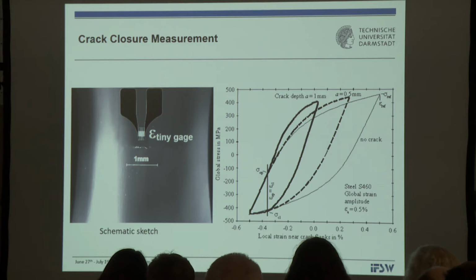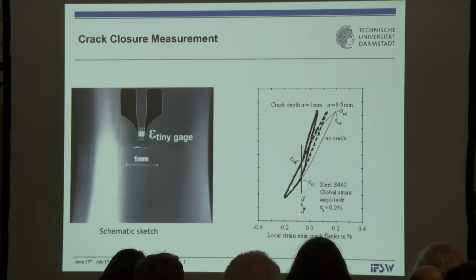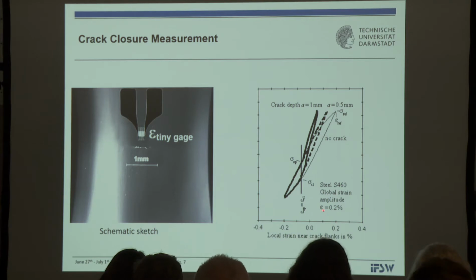This is a figure for applied strain amplitudes of 0.5%, and this is a figure for a smaller hysteresis loop, where the applied strain amplitude is only 0.2%, but the results are practically identical. The loops are a bit narrower, but you identify here the crack opening stress and the crack closure stress, and you can identify a more or less vertical line in this graph to distinguish between open and closed.